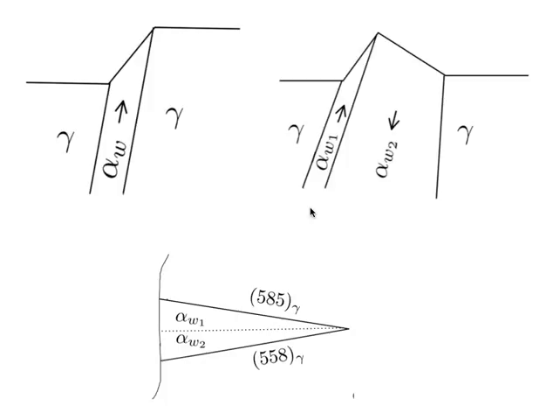What's happening is that there are two plates forming simultaneously which accommodate each other's shape deformation. It forms at a small undercooling — for martensite you had a table showing the strain energy is of the order of 600 joules per mole, which is huge. That sort of strain energy cannot be provided by a small undercooling — the chemical driving force is much smaller than 600 joules per mole. So instead of single plates forming, you have two plates forming together which cancel out each other's shape change.